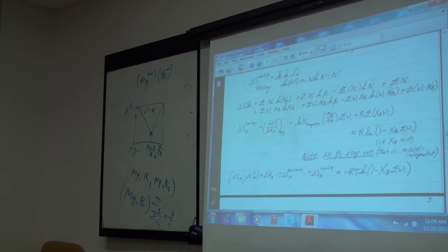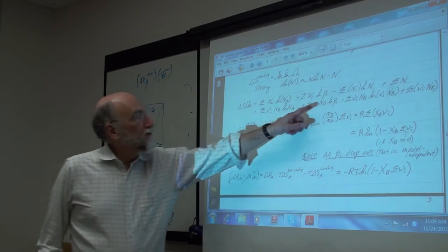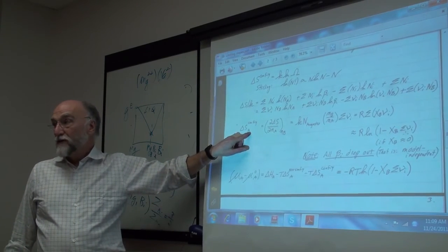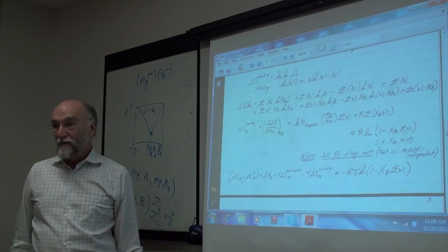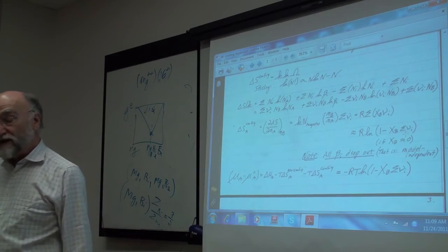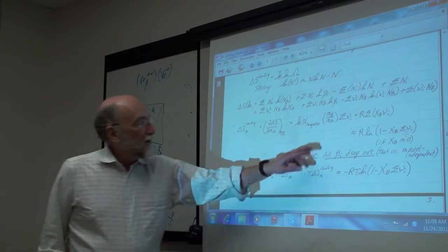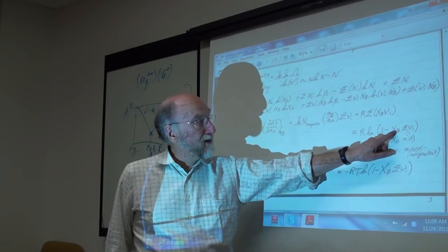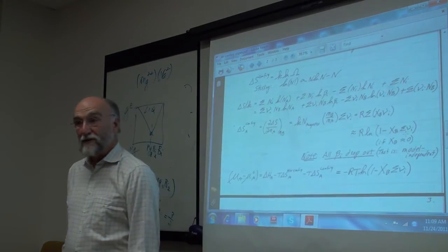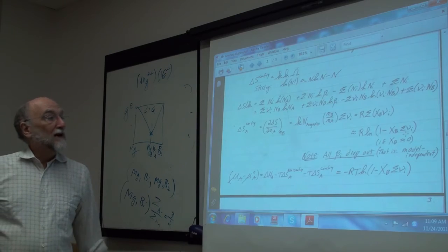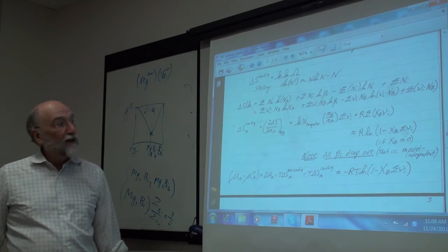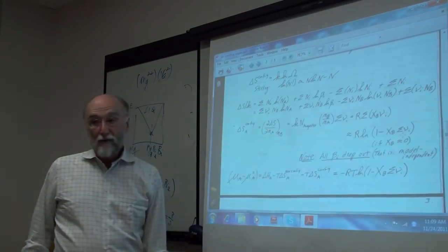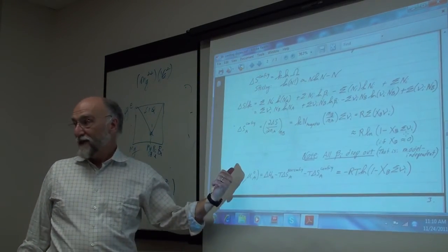And that's all. I'll let you read the whole thing. All these betas will affect the partial property of the solute, but that's not what you care about. All you care about is the partial property of the solvent, which is basically obeying Raoult's law. And you work the whole thing out, your partial entropy is simply R log of 1 minus XB times the sum of nu, which could be looked at as a corrected mole fraction of A. If sigma nu is 1, then 1 minus XB is simply the mole fraction of solvent A.